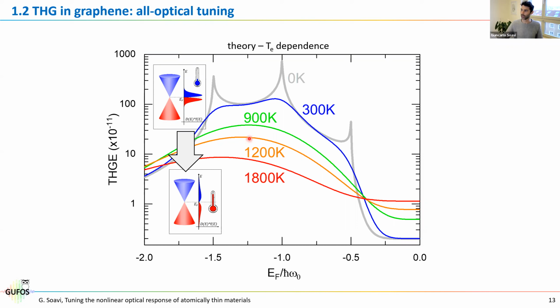And if you now look at what happens as a function of temperature, you can immediately see that the peaks almost disappear, or basically disappear, and you have only one broad curve that includes or merges all these multi-photon transitions. And this is simply an effect of the electronic temperature.